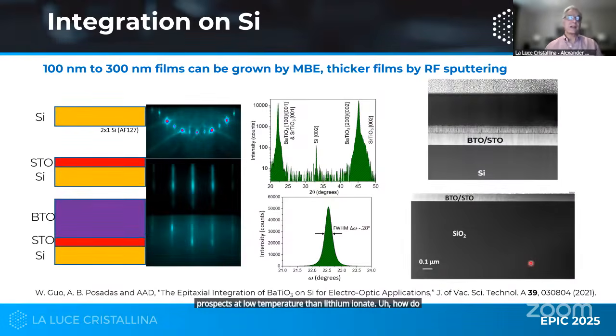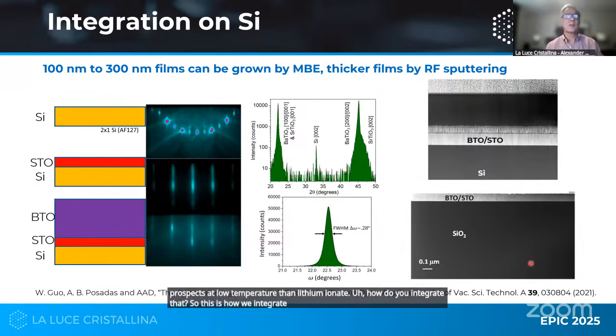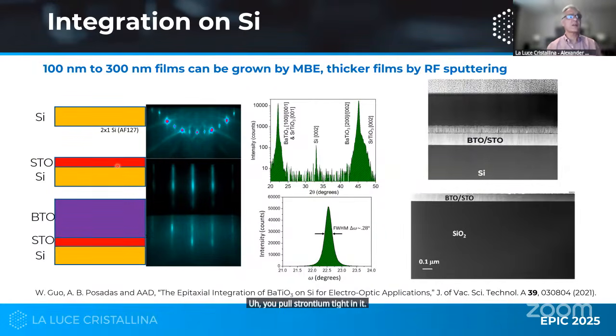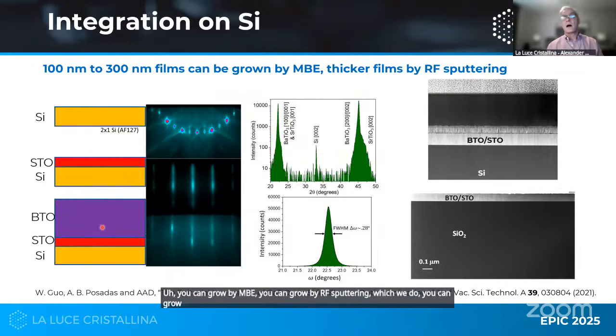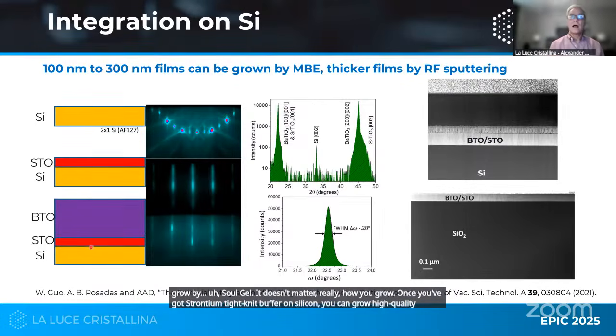How do you integrate that? This is how we integrate, but I think most people do the same thing. You start with clean silicon. You put strontium titanate. It's a buffer. It's a perovskite buffer, reasonably well lattice matched to silicon. And then on top of that, you can grow barium titanate, this purple thing. You can grow by MBE. You can grow by RF sputtering, which we do. You can grow by sol-gel. It doesn't matter really how you grow. Once you've got a strontium titanate buffer on silicon, you can grow high quality barium titanate.